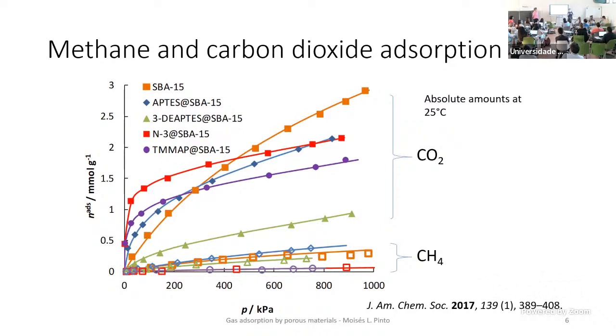So an amount, I will try to highlight this, it's better to express this as an amount of gas. So from the chemical point of view, we should express it in moles or millimoles per gram of solid, per mass of solid. So we have here adsorbed amounts as function of pressure. And if you see in here, these materials are adsorbing more CO2 than methane. So I will not discuss, of course, the results from the chemical point of view, why some are better than others, just to highlight that you have adsorption above the critical pressure, the temperature, and you can use these types of materials to separate methane from CO2. This could be one of the applications, yes?